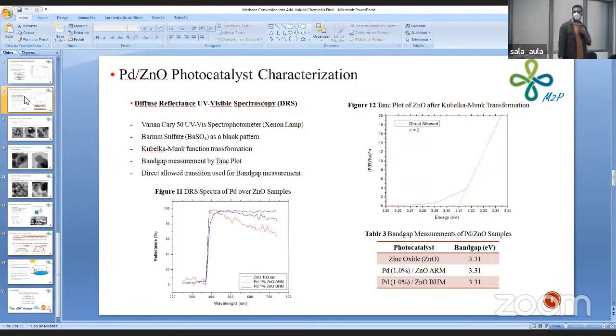samples. This way, we use the Tauc method, represented at figure 12, in order to estimate the band gap of the materials. In table 3, we have the obtained results, and no difference between pure zinc oxide and the palladium-containing samples could be observed. And it happens given that the palladium particles are only on the surface of zinc oxide, and no structural change is happening with the deposition, no structural change in the zinc oxide. So the band gap is the same.